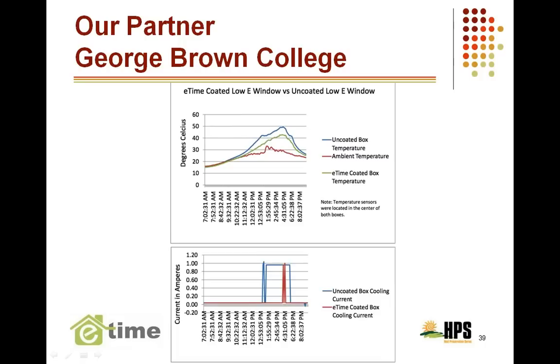When the sun is on the windows, and that's when the coating is actually activated, it has to have sun on the windows. And when it is, what happens is that window warms up. So its temperature ranges somewhere in the neighborhood of about 42 to 47 degrees, regardless of winter or summer. And as a result, that 22 degrees that wants to move to the -13 outside can't penetrate the 42 degrees. It's hotter. And that's the difference between setting up a thermal barrier and acting like an insulator versus reflecting the energy away, which our competitors do. So we're absorbing the energy to create a warmer surface area of the glass, and in turn, it blocks the transfer of heat, either inside in the summer or outside in the winter. And that's the testing that we had, and that's why we reduced the gas consumption by 8% on the Jack Astor's project that's validated. Mm-hmm.